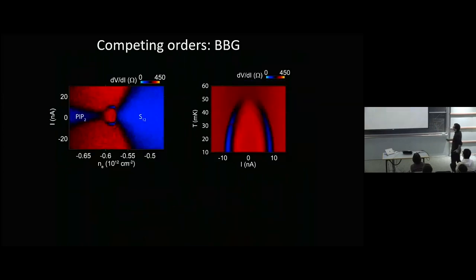Okay, and what we think is that there's some competing phase. We don't know what it is. I think it's interesting to think about. It acts experimentally like a charge density wave in that you have a threshold nonlinearity in the transport, but it's not superconducting. It just looks like you turn up the current, and then there's some threshold current where the resistance drops a little, a sudden drop in resistance. So this is differential resistivity, and this bright blue means there's a spike in differential resistivity, which just means the IV curve slightly changes its slope.